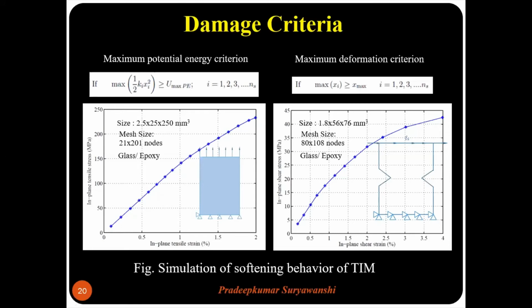Okay. Similarly, we do it for maximum deformation. But we observe that out of these two criteria, the results of the simulation by maximum potential energy criteria were quite in good agreement, and they were quite better compared to maximum deformation criteria. Therefore, in all of our simulations, we have used maximum potential energy criteria whenever we were about to simulate damage in the simulation.